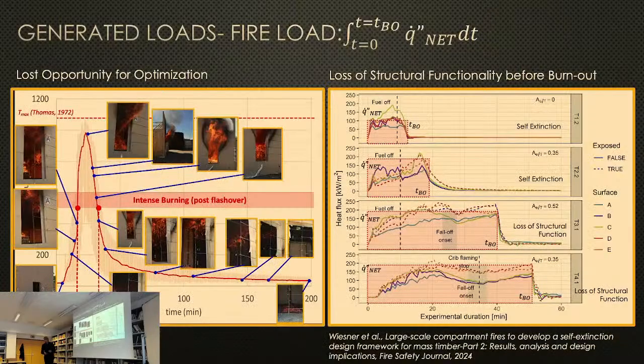So how do you do that? Here's a series of tests that we conducted. And you can see that the fire starts, it grows, it reaches a peak. You have a very, very violent fire happening, and then all by itself, very rapidly, it dies out, and then you get self-extinction. Now, if you play with the different conditions, you find how the QNet starts evolving, and you can find conditions by which your time to burnout is 15 minutes, in which case you get a very thin char layer, and you circumvent all the complexities of the problem.